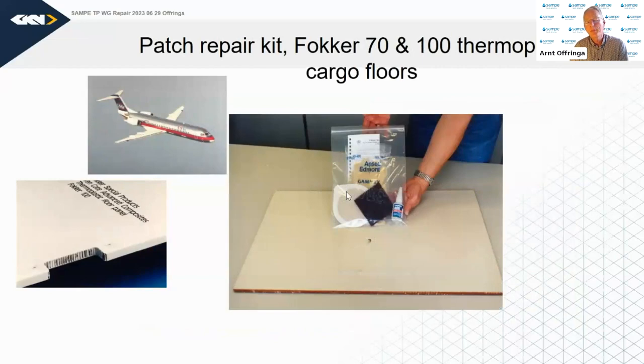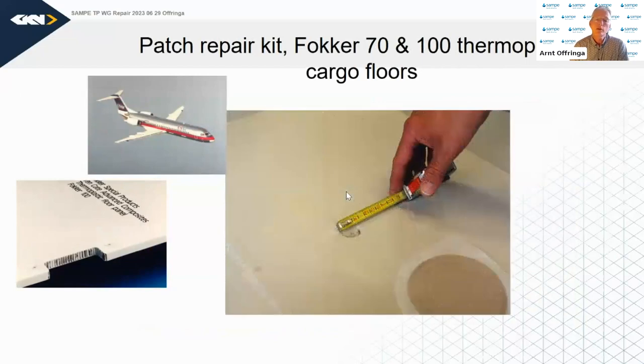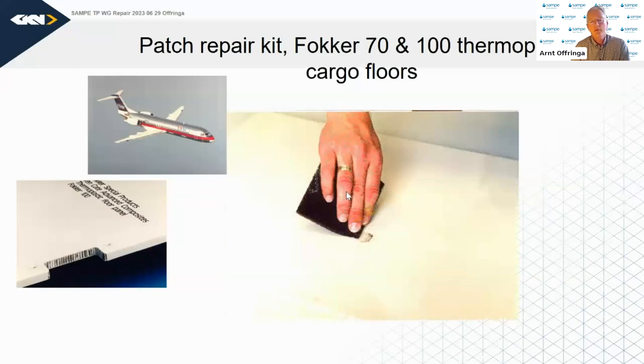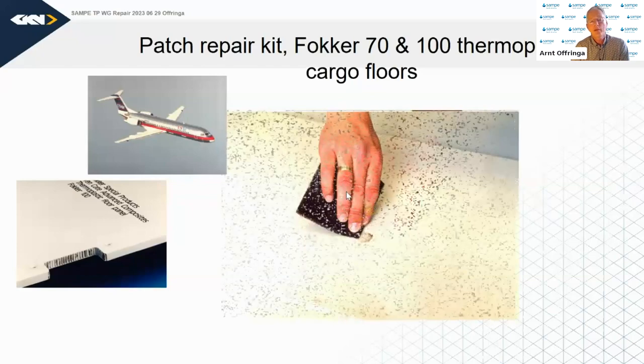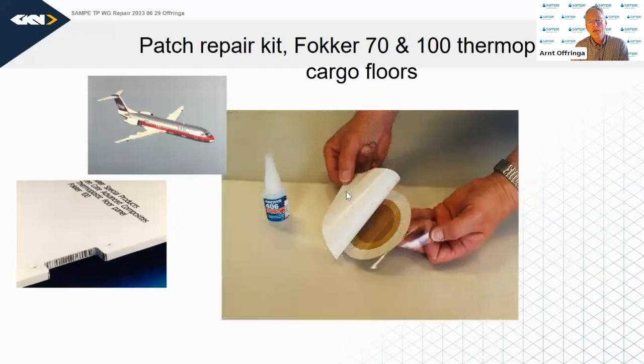So kind of a repair kit was developed, much like a bicycle tire repair kit, very easy to use with instructions. And this repair kit starts with a measurement. So you see there, it's a metric measurement, 2.5 centimeters, 1 inch. If the damage, a perforation in this panel, in this case, is less than 1 inch, you're allowed to perform the cosmetic repair. And the way it works is you sand the contour of the repair area, you clean it with alcohol, then you take your patch, which has been pre-manufactured, and it's a tapered patch, so it gives you a nice and smooth surface.